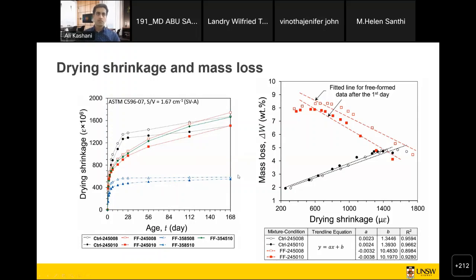The other thing is in terms of the shrinkage and mass loss. Here you can see there are two things. One is the shrinkage that's happening in the first 24 hours, which is not shown here, but in the first 24, 48 hours, the amount of shrinkage is much higher for the free-formed sample compared to the cast sample. This is not mainly based on this study. We are also using another study using strain gauges in real conditions in order to understand that, and this is our observation.